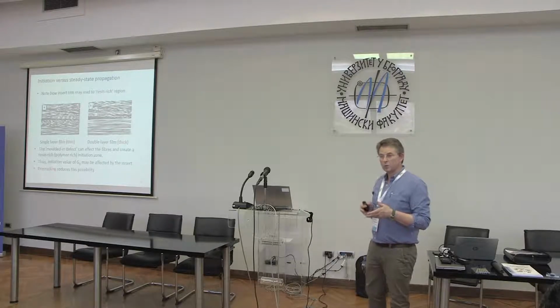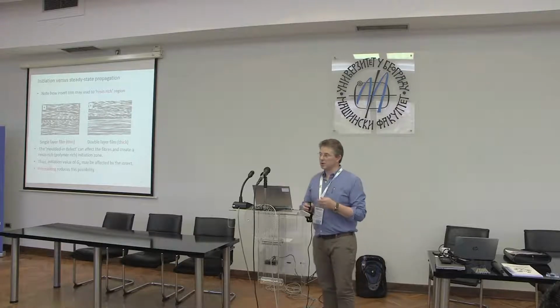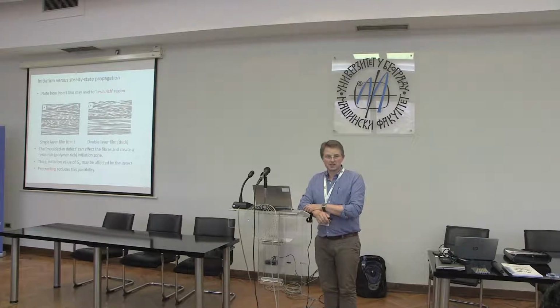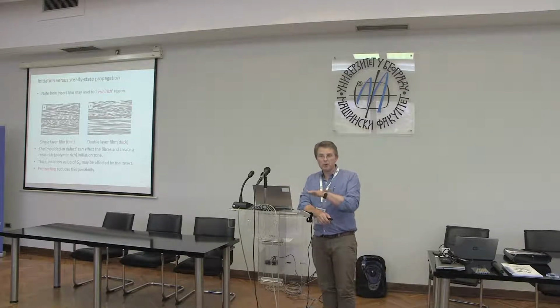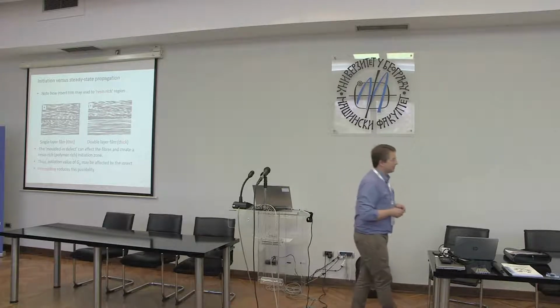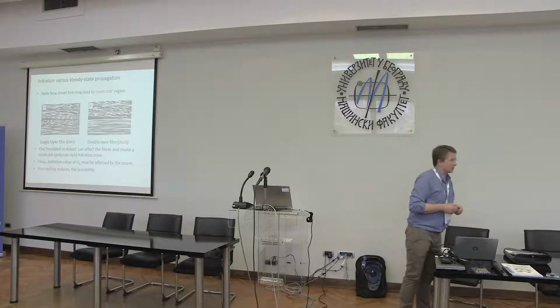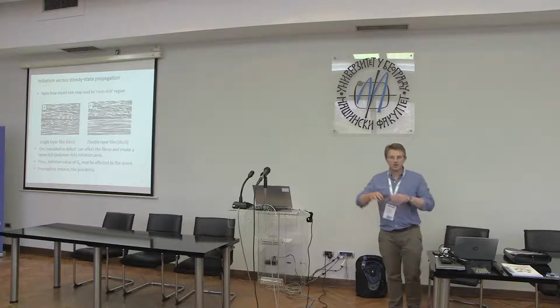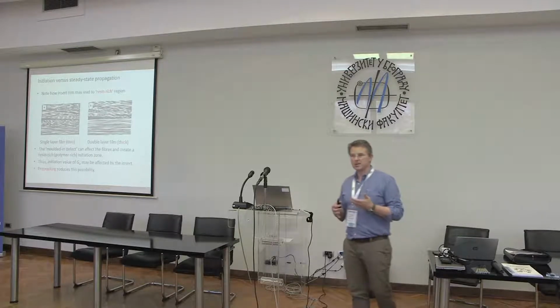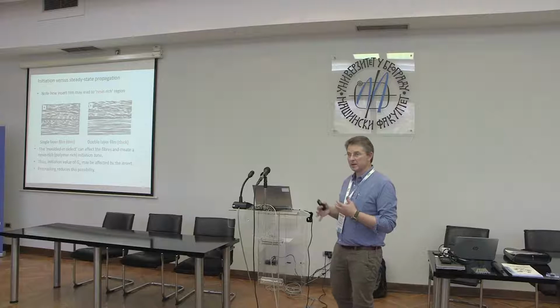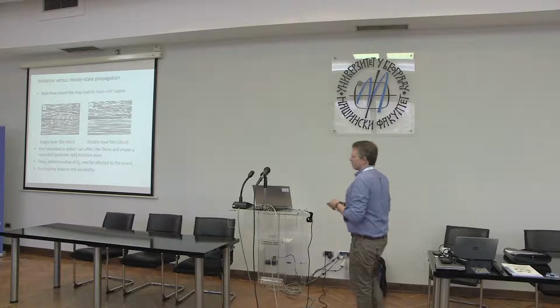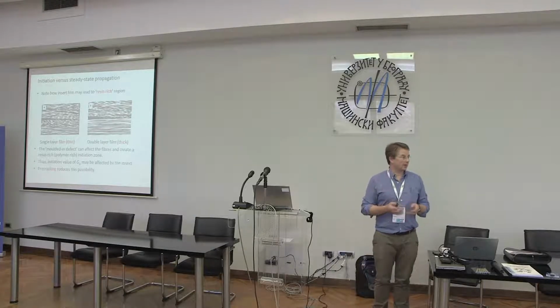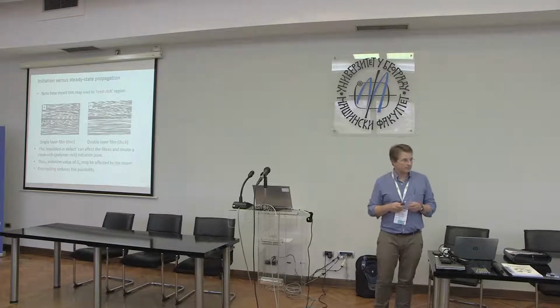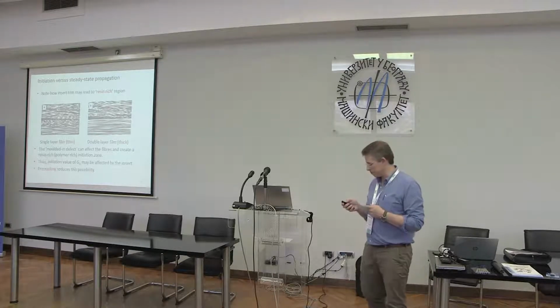And of course, one of the things that you have to make sure when you develop a fracture mechanics experiment, a specimen, is that you're not introducing an artifact into the behavior. So when we mould in our sheet of PTFE film at the mid-plane of the composite, are we changing the material at all? Is there any other change to the material that wouldn't have been there otherwise? And of course the answer to that is it depends upon the thickness of the film that you embed. And this diagram explains what I mean actually.